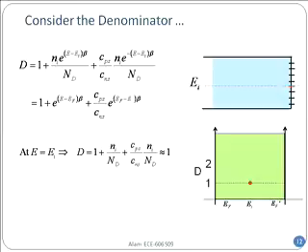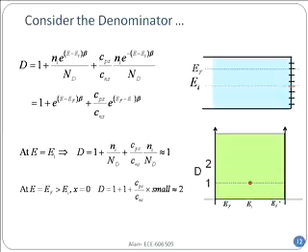So I have 1. You can see I have shown here in the red graph on the right hand side, at the point where it is EI, that the magnitude is 1. The denominator is 1. Now what happens in the denominator at E equals EF? If E equals EF, then from the previous slide you should put the expression E equals EF, and the value for X, which is the difference between E and EF, will become 0. So X is 0. If you put X equals 0, then you will see that at that point the value of the function will be 2, right?